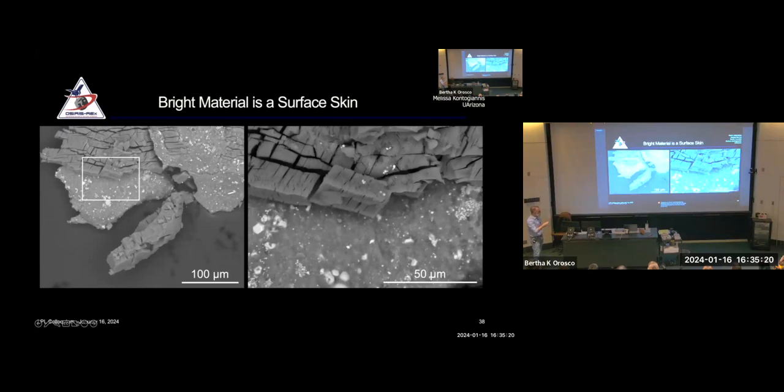If we zoom in on that box that I showed you on the previous slide, you can see here is what looks like the main lithology. And the reason I say that, some indicators, you see the little hexagons, which are the sulfides, and I also see the framboid magnetite. This looks like the clay-rich material with the embedded sulfides and oxides and minor phases, and the phosphate looks like it was a vein or a crust or a surface skin.